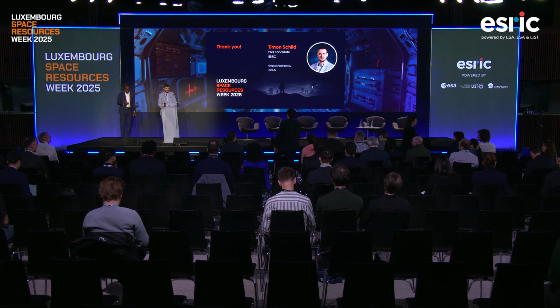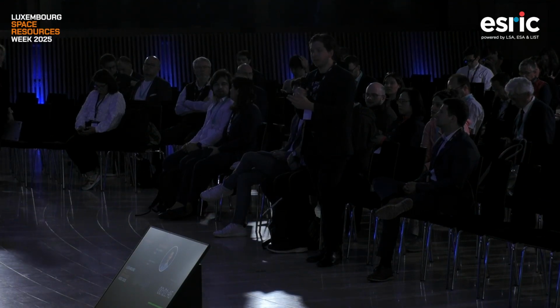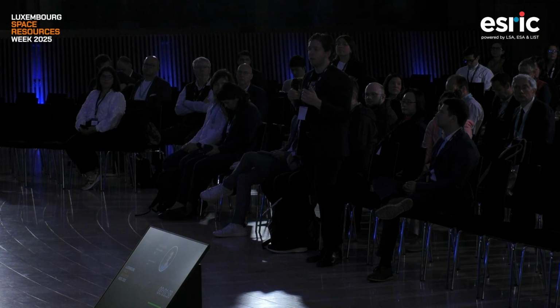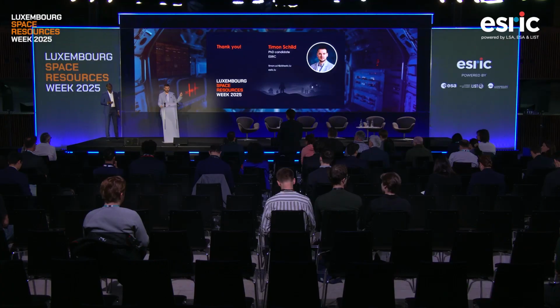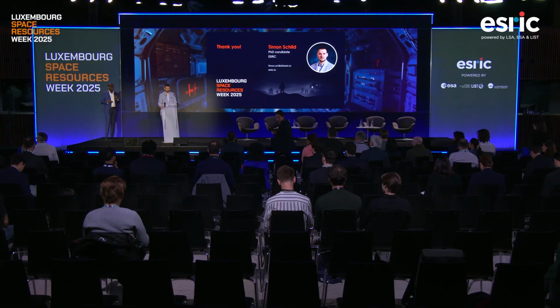I'm Aaron Shamatsi, and my question is, did you have a chance or did you attempt to do the melting of the product in argon atmosphere, for example, in an argon glove box, where you can control the atmosphere to avoid potentially the surface reoxidation? So the melting process I've been showing, we did it actually in helium. Helium 6.0, so actually a lot of our work was making sure that the oxidation is not coming from the outside and not related to our setup, but that it is actually a behavior of the material itself. Okay, thanks. Thank you, Aaron.